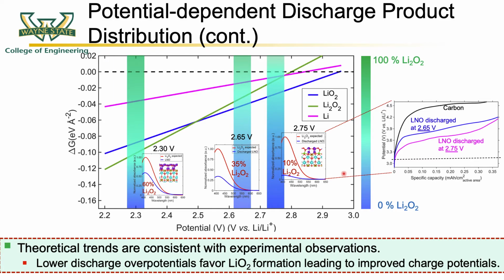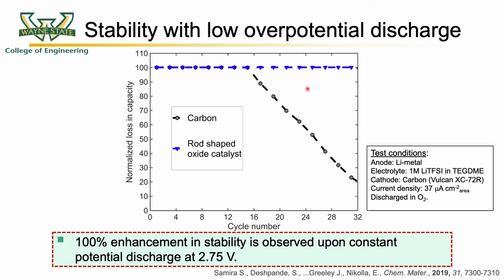This validates our theoretical predictions and our hypothesis that the selective formation of LiO2 on these oxides leads to the enhanced catalytic performance. The lowering of this charge overpotential also results in an enhancement in the stability of these electrodes.